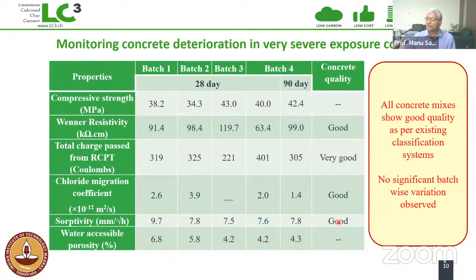As you can see, up to 90 days, all the tests are really good in terms of the very high resistivities that one can expect from such concrete. You also get very low chloride permeability as measured by the RCPT test, and an extremely low chloride migration coefficient, which are typical of high performance concrete. You can see these numbers are typical of high performance concrete.